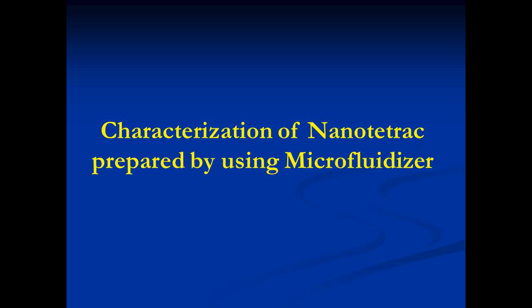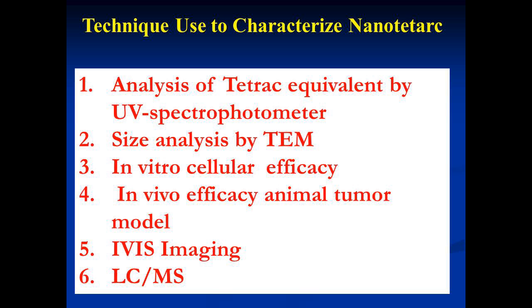All those nanoparticles, NDAT or nanotetrac, we analyzed using a UV spectrophotometer to see how much tetrac equivalent is conjugated in the nanoparticles. The size was analyzed by transmission electron microscopy. We also check the cellular efficacy and in vivo efficacy in different tumor models in mice, then IVIS imaging, which shows us where the dye-conjugated nanoparticles are going in a live animal. The amount of tetrac or other drug in the nanoparticles can be measured by LC-MS. Those are the different characterization techniques we used after synthesizing the nanoparticles in the microfluidizer.